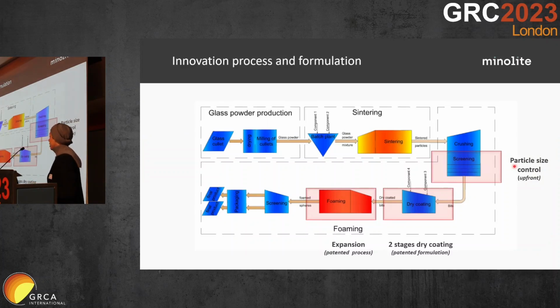This is the flow chart of our process. As I mentioned, we have the glass powder preparation, and after that, high temperature sintering. And then we crush the sintered material and screen it. There is an innovation step here where we screen the particles before expansion, which means we have full control over the size of the product.